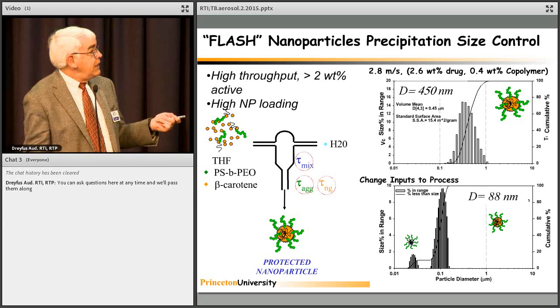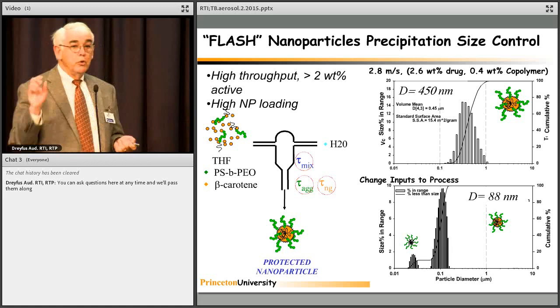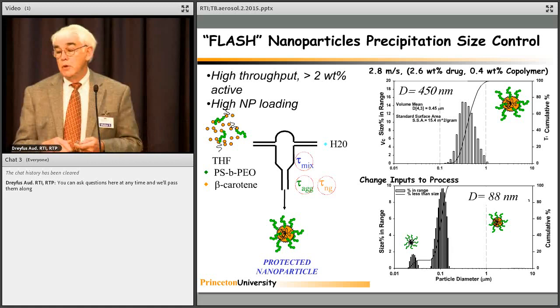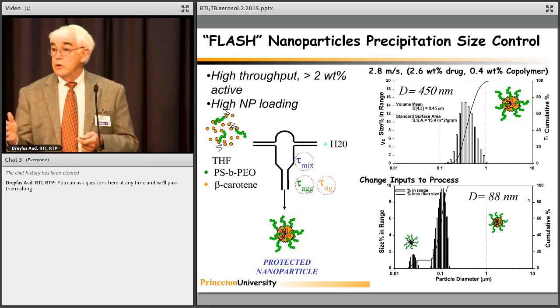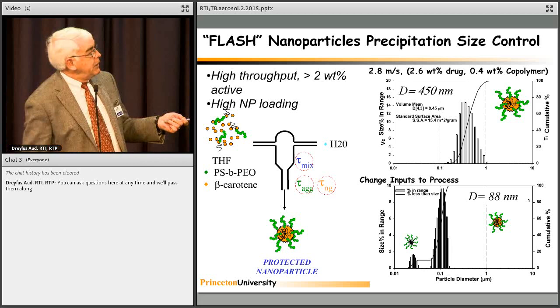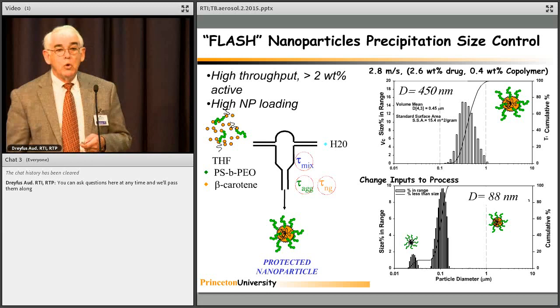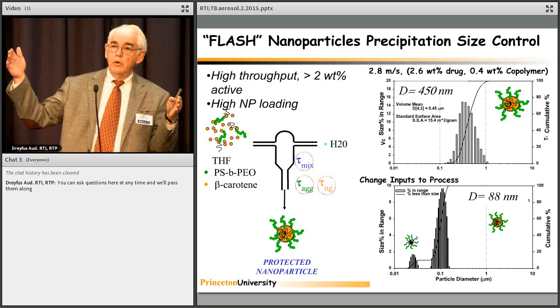Importantly, nothing is above 0.2 microns, so you can take this and put this through a 0.22 micron filter and it's sterile, and that's a big deal for a lot of our collaborators, industrial collaborators, to be able to form and post-sterilize these, especially if you're looking at biologics that you don't want to put through heat treatment for sterilization. We have a little bit of excess polymer, a block copolymer in this one, and those are free micelles that are formed. So we had a little more polymer than we needed. So this size range of about 50 nanometers up to about 500 nanometers is where we can conveniently get with this technology.